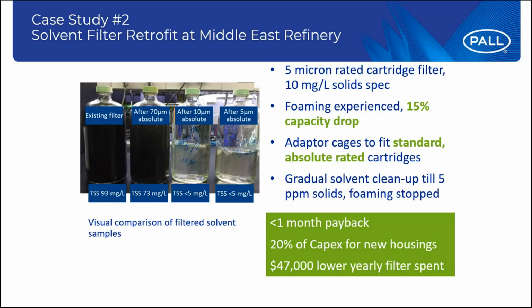He had to reduce capacity by 15%, and with Pall support we could adapt and retrofit the existing vessel by using some adapters, and very quickly the quality of the amine improved to values below 5 ppm. Visually you can see a very spectacular switch to a very clear and transparent solution. That helped the customer save on capex, with no investment required for a new installation, and he also reduced his spend since the installed filters had a higher capacity, so the change-out frequency was reduced.